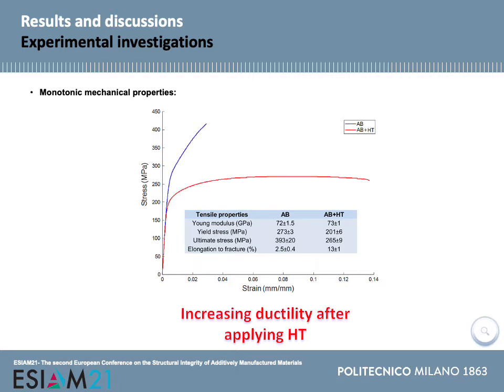After explanation of the experimental procedure and also implementation of the deep learning, here I want to present the results and discussions. The results and discussion section is divided into 2 different parts: experimental results and modeling results, which are obtained by the neural networks. Firstly, I would like to mention the mechanical properties. It can be seen that by applying heat treatment, the elongation is increased from 2.5 to 13, which shows high increase in ductility of the material after heat treatment. Also, the values of yield and ultimate strengths were slightly reduced after applying heat treatment.